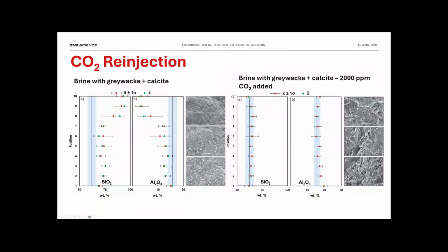What is interesting about this experiment, this is a different experiment than the other one, is that the silica is thicker at the top of the pressure vessel. So remember, the fluid's entering here, but it's exiting here. But the actual silica is actually thicker at the top of the pressure vessel this time than at the bottom, as I showed you previously. This points out the importance of the difference between different fields, different rocks, different brines. I've done many of these experiments, and I tell you, almost every one of them is different. This is something to do with the kinetics of the silica precipitation. It's actually being delayed, and then as chemistry changes, as the fluid moves up the pressure vessel, it triggers faster silica precipitation.